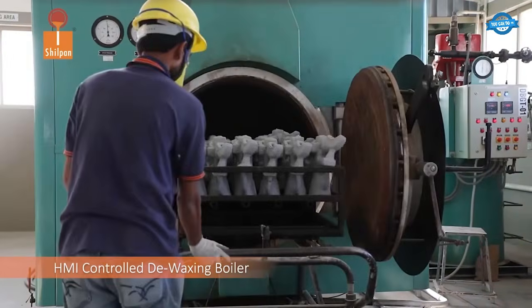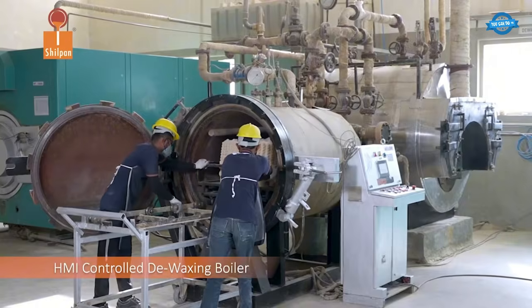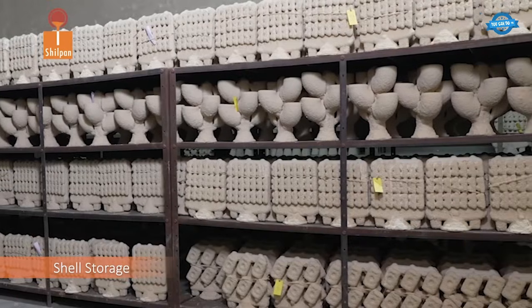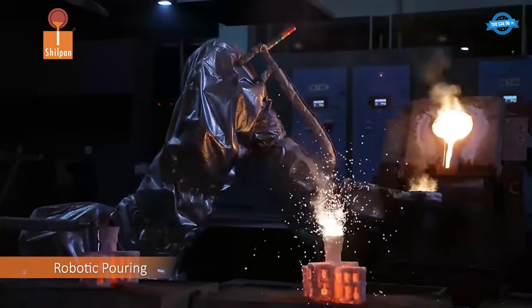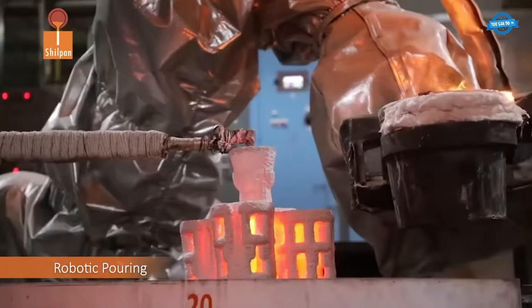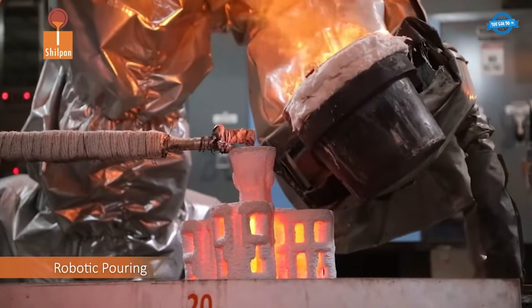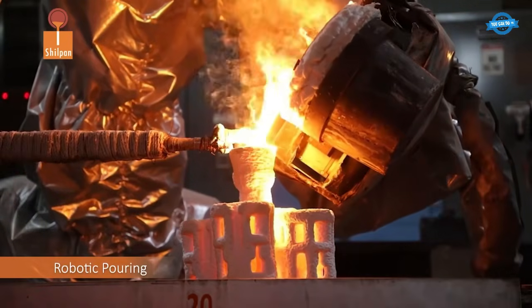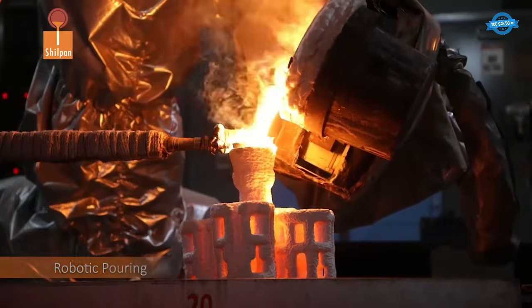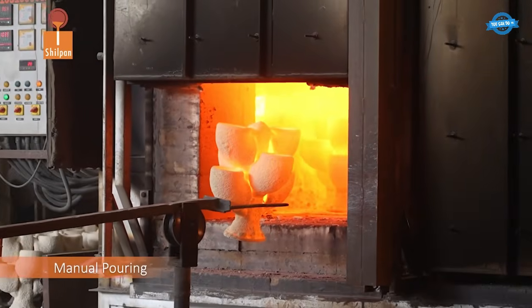Induction furnaces melt the alloy at over 1,500 degrees Celsius before pouring into the preheated shells. Why preheat the shell? Because dumping 1,500 degrees Celsius metal into a cold ceramic mold shocks the ceramic and the whole tree ends up on the floor, along with the entire day's plan.